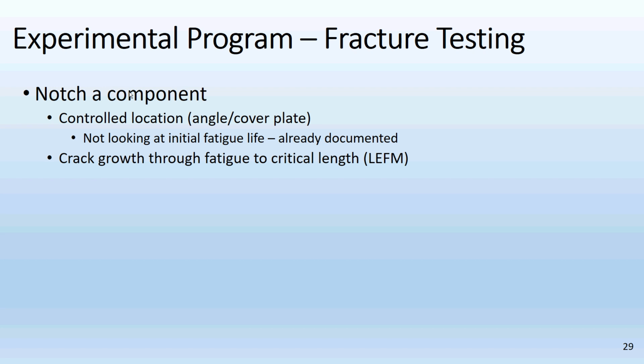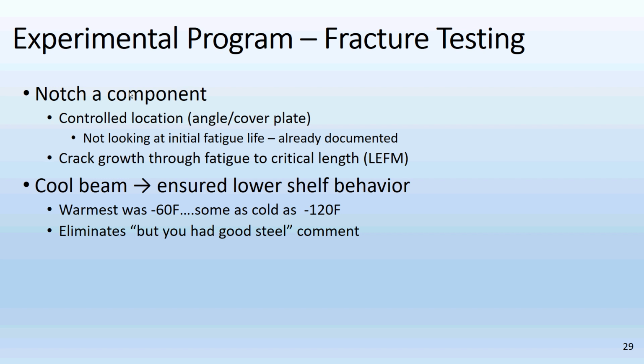Basically, the researchers built some full-scale and large-scale specimens, and notched a component, say an angle or a cover plate. The reason we would notch them is to get a really sharp, true fatigue crack. We don't care about initial fatigue life. That's well-documented, well-researched. We would then grow that crack to a critical length based on fracture mechanics, and that required the girders to be cooled in some cases, but note the temperature: minus 120, and the warmest we tested was minus 60. That's zone 3. We would get down to minus 120.